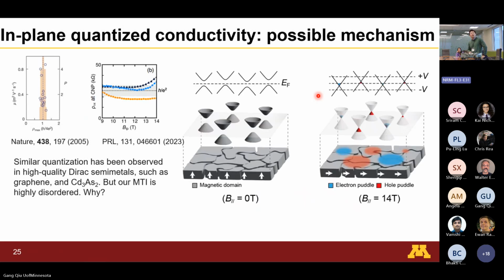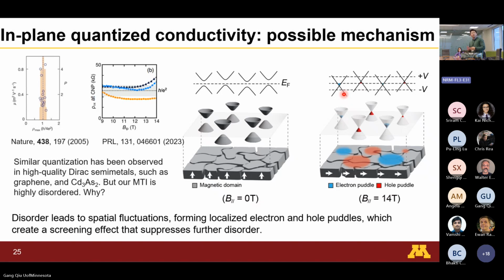At this point, we don't know much about why this in-plane quantization happens. We have some initial guess because there are some defects in these magnetic topological insulators. If you look at the Dirac cones, there will be a lot of ups and downs. If you cut the Fermi level inside, there will be some electron and hole puddles created. At some locations it will be p-type, at some locations n-type, and these correlated electron and hole puddles perform a screening effect to avoid further disorder. So the resistance actually saturates at a quantized value. This is just our interpretation. We still have not fully understood these results.